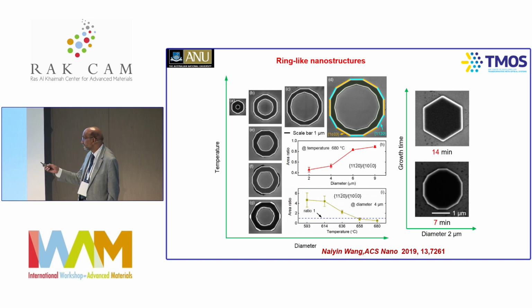If you keep on growing further, then this gap gets filled up and you create a nanomembrane. In this case, it's sitting in the horizontal way. You keep on growing further, ending up finishing off these nice hexagonally faceted structures, because crystals like to be in the low energy facets, and that's what you end up having. And again, they are very useful for MEMS applications and nanomembrane lasers and a range of things which we're exploring at this stage.